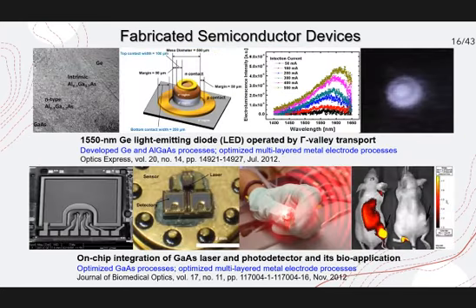And then the germanium light emitting diode, with a 1550 nanometer wavelength, is the standard bandwidth channel for long distance optical communication. But in order to achieve that wavelength, ternary or quinary compound semiconductor materials should be prepared with very accurate control over individual atomic fractions, which is very critical and tricky in semiconductor processing. But you can imagine how beneficial it would be if that optical communication channel can be provided by a single species material. That is germanium. But one drawback is that germanium is technically an indirect bandgap material.